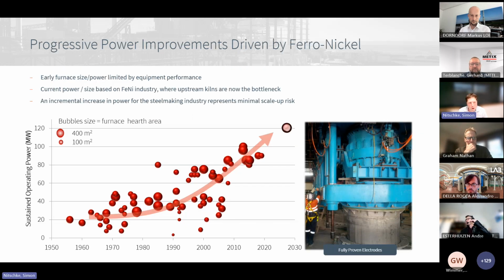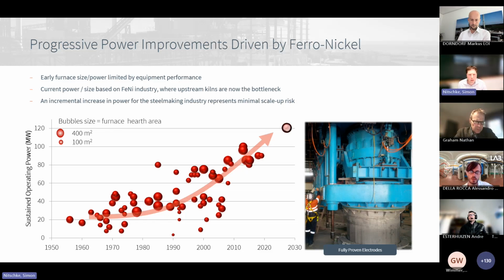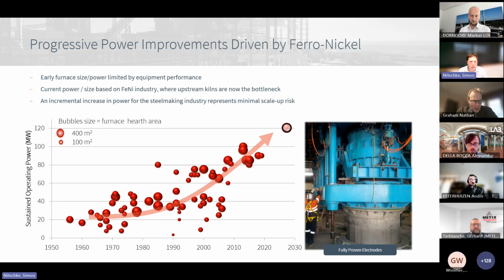So I'll just pause for a moment, and sometimes we get the question around the scaling of the furnace power to the levels that we need, around that 120 megawatts mark. And as I mentioned earlier, we certainly have examples of Hatch furnaces operating around the 100 megawatt mark. And it's useful to reflect on the evolution of that smelting intensity in furnace design over time. So at Hatch, we've developed larger, higher power furnaces over a sustained period of time, as you can see on this plot. And the step to 120 megawatts is easily foreseeable as far as we're concerned, using existing technology and